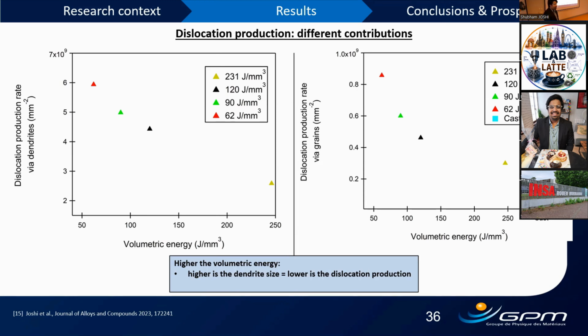You said the dendrites are not quite sure that are the key parameters. Those dendrites have some sort of anisotropy with a main direction. They are formed during the solidification process, which means that they may have some sort of global anisotropy in that orientation, and we reduce them to a scalar. So my question is, do you think that this dendrite orientation plays a role on the macroscopic response? And if so, how could we include that? And if not, why?